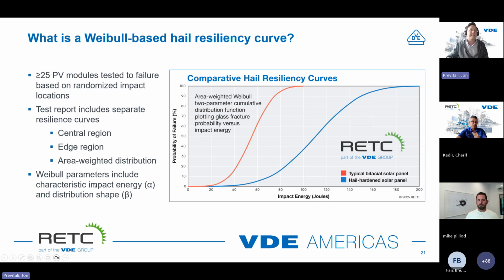And the way we came up with that curve is we take that data, basically the failure data compared to the impact energy, and we plot it using a Weibull approach developed by an engineer and scientist named Weibull in the mid 20th century. And what we come up with are these Hail resiliency curves, as shown here in this chart.